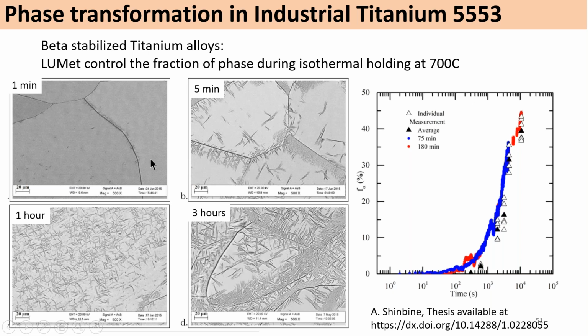Those studies are not always very easy because it involves thresholding the color of gray. So it's always a little bit difficult for individuals to find the right threshold and obtain consistent measurement on the phase fraction. Whereas using Lumet, we let the sensor capture the change in the velocity, and we simply then have to normalize the velocity change so as to obtain the phase fraction.